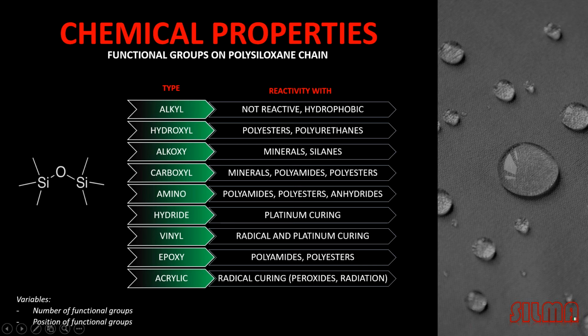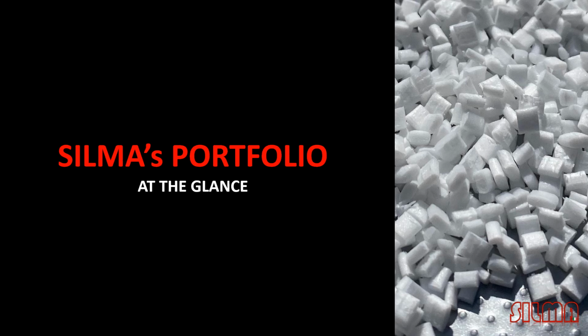But of course, there is not only one type of polysiloxane. The polysiloxane can be modified, changed thanks to many different types of reactive or functional groups. This is the list that you can imagine. You can have the alkyl, which is the hydrophobic group. It can be C8 or C16. Hydroxyl, the same OH group as in alcohol, which makes this functionality reactive with polyester and polyurethane. Alkoxy groups are reactive versus silanes and versus minerals.